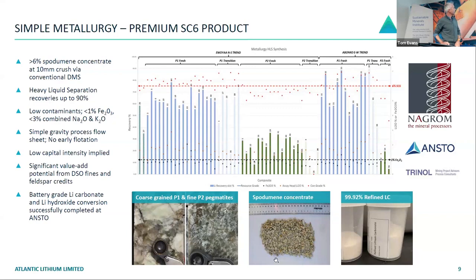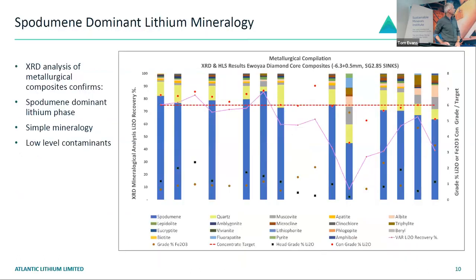And we've also demonstrated that we can convert that to hydroxide and carbonate, which was done here at ANSTO, but that's not really our focus. We're about producing a spodumene concentrate. And we're able to produce this concentrate through a simple DMS-only process flow sheet without having to go to flotation.